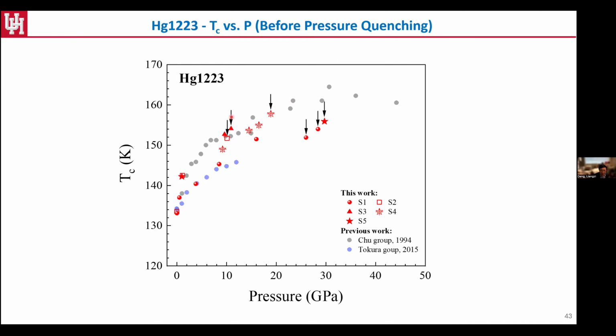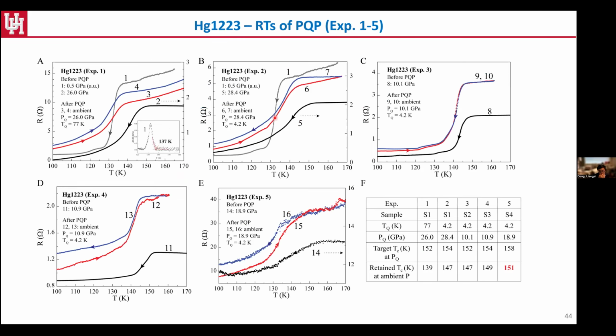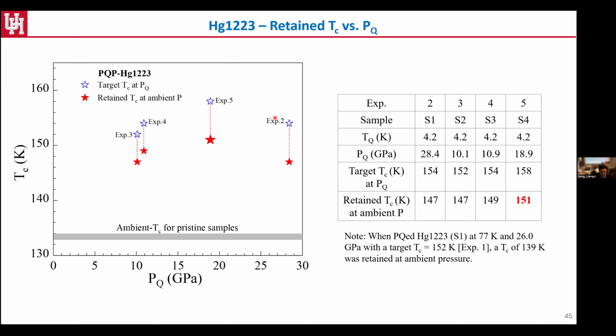So all those arrows pointing at other points, we applied pressure quench later on, right? So here is a quick summary of some of the experiments. We did more than 60, 70 measurements so far, and the success rate is pretty high, around 60 to 70%, which includes cases where sometimes we quench and the diamonds break or leads break. So the highest TC we retain so far is 151 Kelvin, as mentioned here. Just to summarize, we quench at different pressures, and once we quench from 4.2, we get a retained temperature above 145, and the highest we saw is 151.